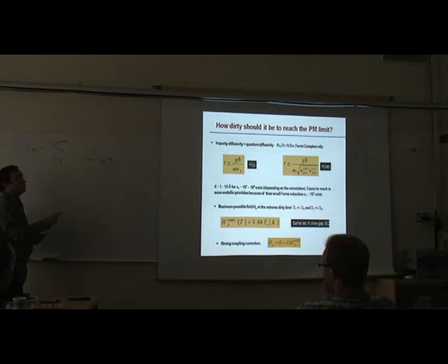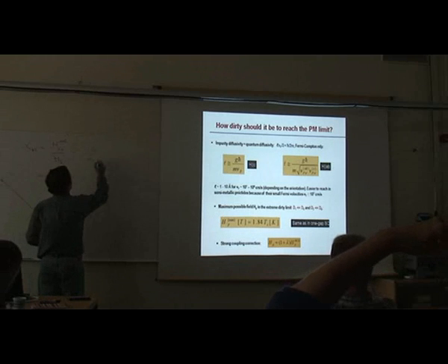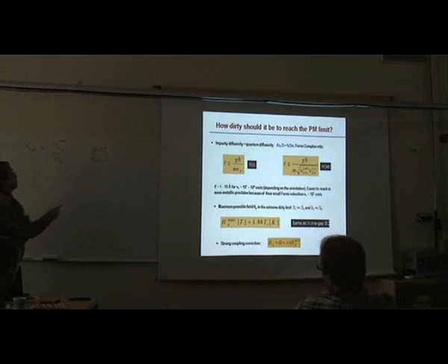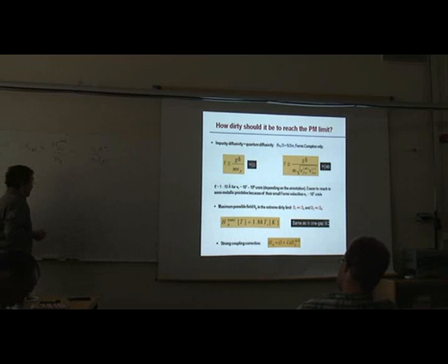Pauli effect. However, if the superconductor is anisotropic, you see that it's inversely proportional to the Fermi velocity along the c-axis, and if the Fermi velocity is small, like in the 2D case, then paramagnetic effects become really important. Or, if we have a very heavy mass, then we can write it like this. That will be the band mass. Sorry, the other way around. So in heavy fermions, this ratio can be about 1,000, so this parameter can become large. That might explain why Pauli paramagnetic effects are very pronounced in heavy fermions. But in pnictides, they are simply important because the Fermi energy is small.